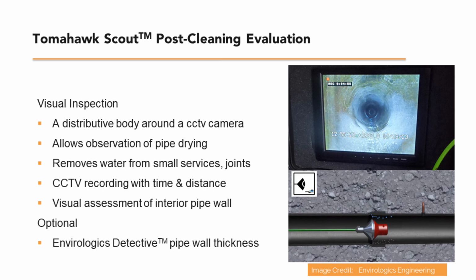An optional step available at this time is to deploy an evaluation tool to determine the remaining wall thickness in the iron host pipe. In the event the project objectives are not adequately informed, remaining wall thickness can guide on-site engineering decisions, including selection of a lining thickness, specific locations requiring repair, or identifying the need for cathodic protection.